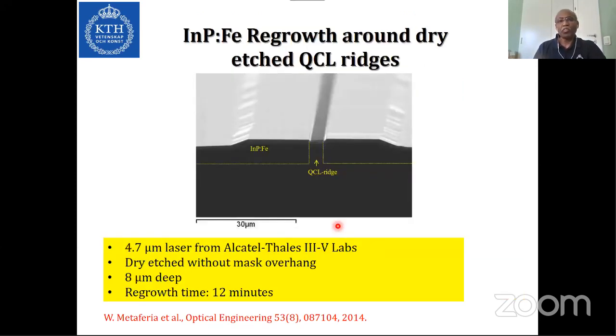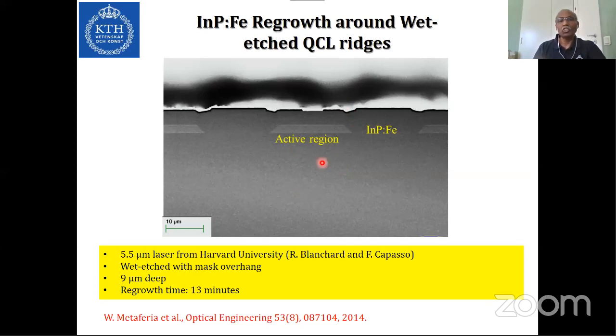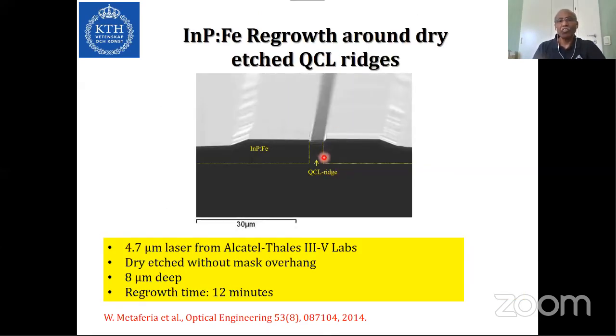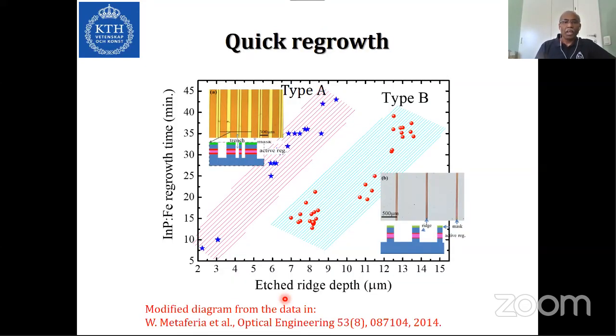And not only wet-etched mesas, but also you can use ridges which are etched by dry etching, and you can also do regrowth without much of a problem. And this is 8 micrometers deep, and it was regrown in 12 minutes. And this is just a collection of several runs we made. This is the type of ridges we have made. And this is a very simple kind of trench structure.